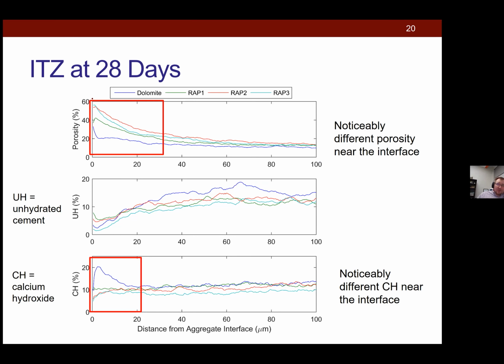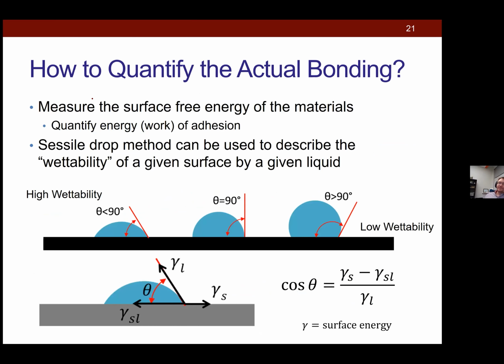So what's the cause for that? That's something I'm still looking into. We're running some experiments at Virginia Tech now to try and answer some of those questions. So I don't have all the answers, right? But at least empirically, this seems to give a pretty good indication why we are seeing a reduction in strength and modulus, right? So now already if we just have a larger, more porous ITZ, right? So now if you look at the total volume of your concrete, you have a larger proportion of that volume that's this larger, more porous ITZ, right? So that already was one thing reducing our modulus.